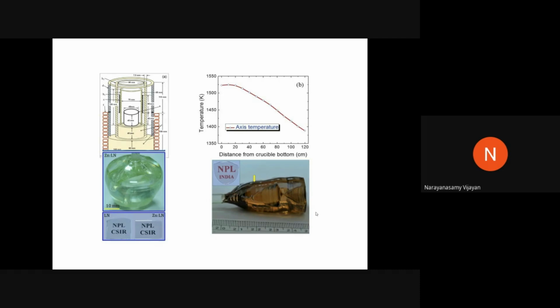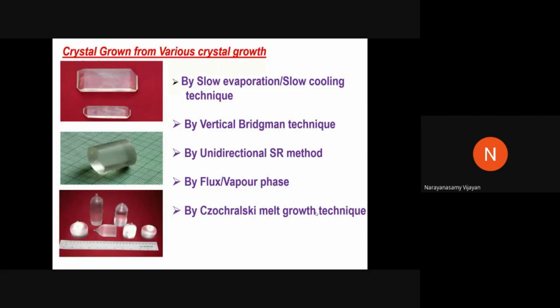Whenever you are working at very high temperature, what will happen? Sometimes when you come to room temperature, cracks will form, and the cracks indirectly generate a lot of defects. To avoid that, we took only the RF furnace and made the resistive heating ourselves, and we have grown varieties of single crystals.